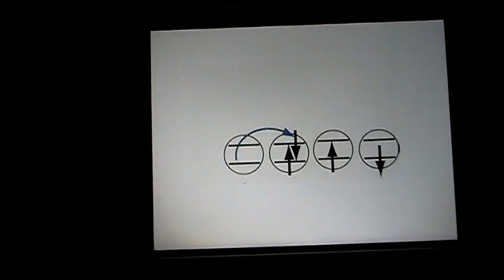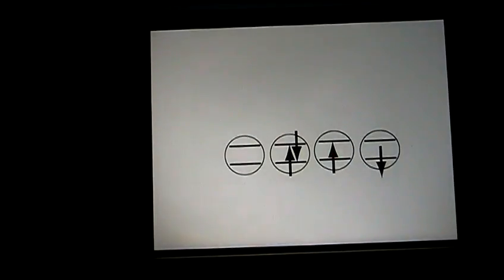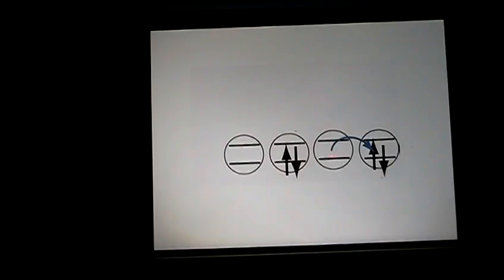So it's going to put this electron into an excited state, and not necessarily on this atom. This could be delocalized. It could be a band. But this atom now, whatever it may be, is going to be charged. And because I'm dealing with a Mott insulator, an extra charge on this atom is going to push the electron on a nearby atom to go to another one and create double occupancy. So at the end of the day, I end up with two doubly occupied sites and two hole states from this.